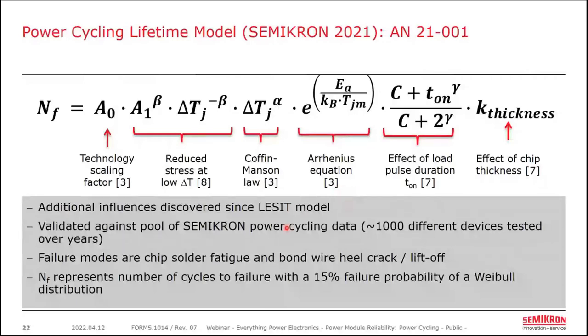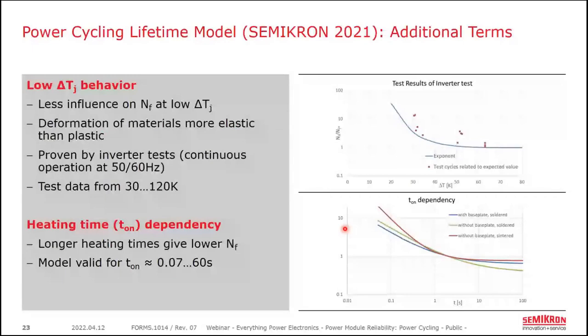And as with any failure rate prediction, this model has to be looked at as part of a bigger statistical analysis. And the particular coefficients that we give are valid for a 15% failure rate. And so two of those additional terms in there that are not in that original LESIT model are the low delta T behavior and the heating time.